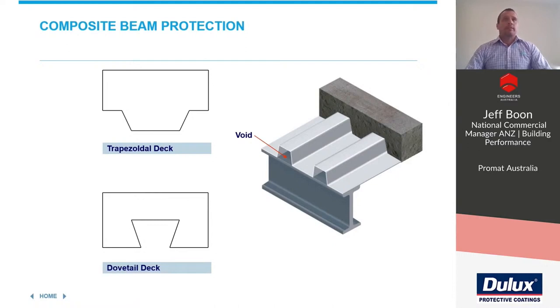For metal decks such as Bondek or Condeck, with smaller voids, nothing additional is required. For larger voids, they will need to be filled with the protection material used to protect the steel section or filled with high-density mineral wool, unless there is test evidence showing that this is not required. If the beam falls on a compartment barrier, then all openings must be blocked no matter what the size.